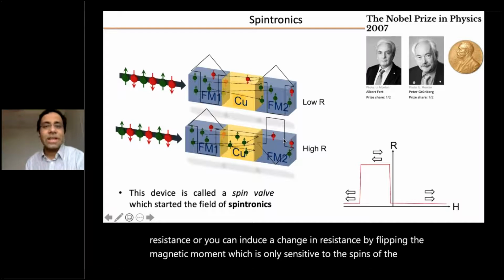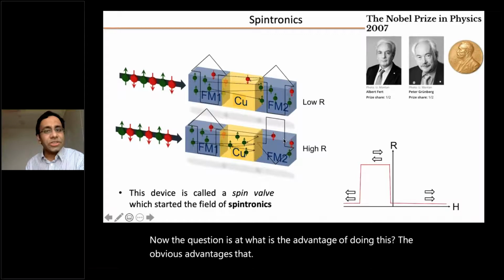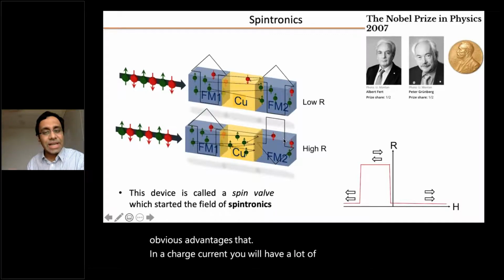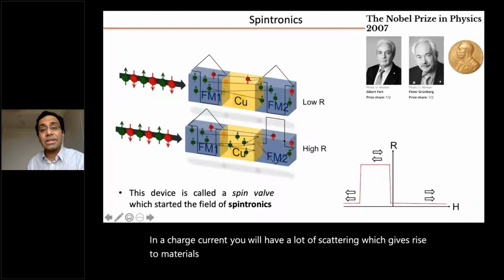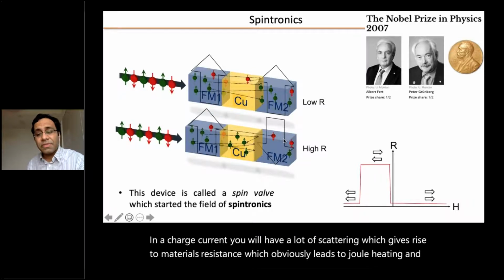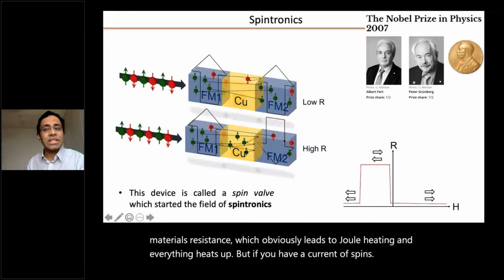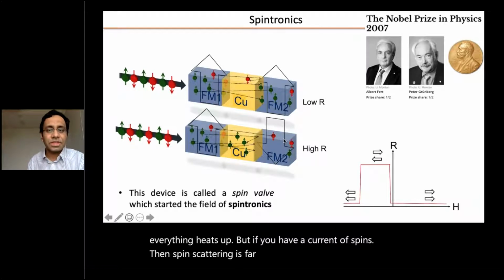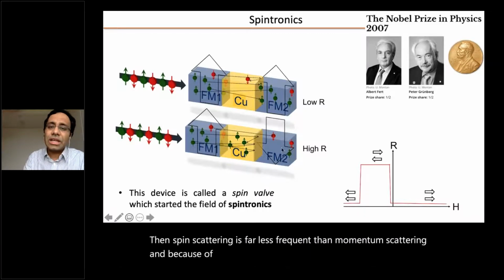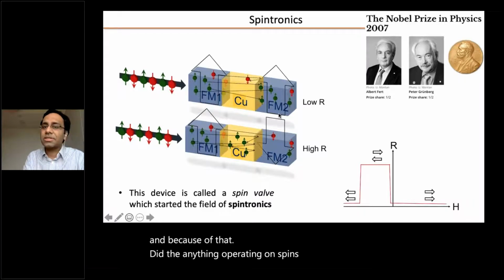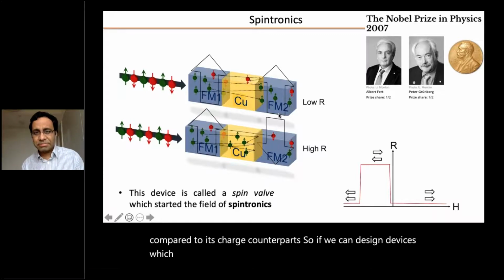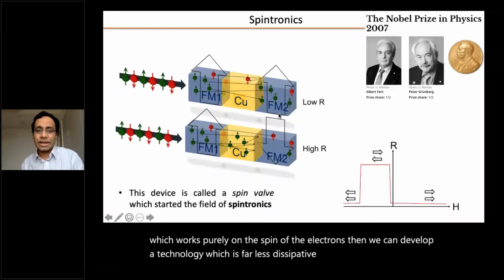Now, the question is: what is the advantage of doing this? The obvious advantage is that in a charge current, you will have a lot of scattering, which gives rise to a material's resistance, which obviously leads to Joule heating and everything heats up. But if you have a current of spins, then spin scattering is far less frequent than momentum scattering. And because of that, anything operating on spins will have much less dissipation compared to its charge counterpart. So if we can design devices which work purely on the spin of the electron, then we can develop a technology which is far less dissipative than charge-based electronics.